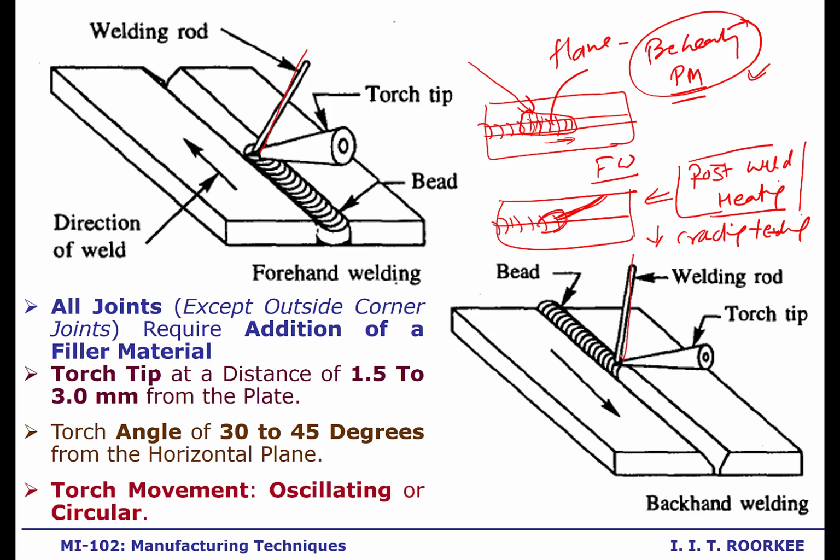And these are the other aspects, like how the filler rod is placed. Invariably in the case of thick section welding, where a V groove has been made like this, we need to use filler. Filler of matching properties in terms of composition, mechanical properties, and physical properties is usually preferred, so that the joint strength is similar to that of the base metal.